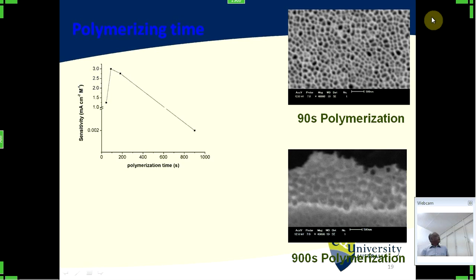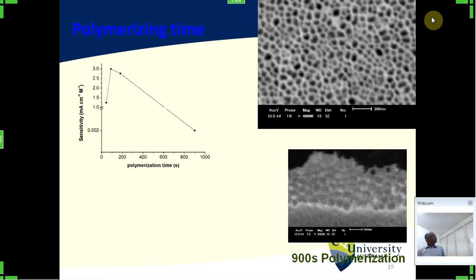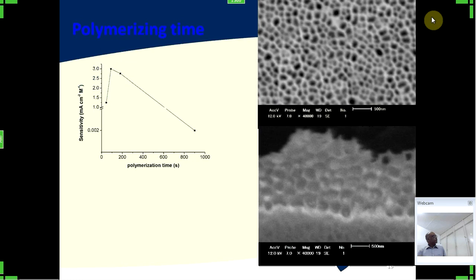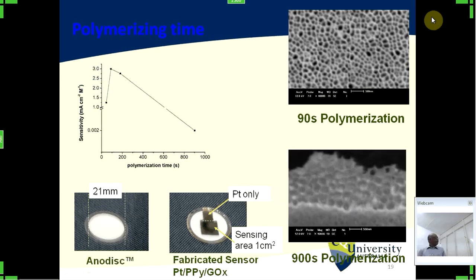So in 90 seconds, we got very good nanotubes in this one. And this is not the electron microscope image, this is a normal image from a camera. This one is masked and deposited, and we make a 1 centimeter by 1 centimeter layer and put an insulator layer here to stop the polypyrrole developing on this part as well, because this is again deposited platinum. So finally we make 1 centimeter by 1 centimeter PPy.